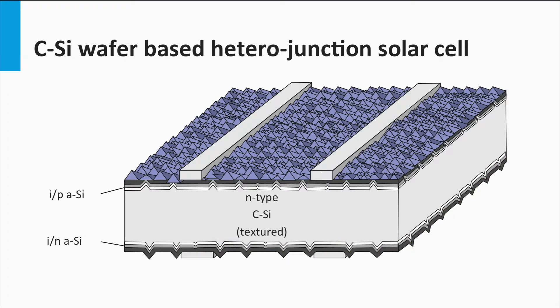How do the charge carriers travel to the contact? The conductive properties of the P-doped amorphous silicon are relatively poor. In the homojunction solar cells the diffusion to the contacts takes place in the emitter layer. In contrast, in a HIT solar cell this occurs through the transparent conductive oxide material, like an ITO, which is deposited on top of the P-doped layer.